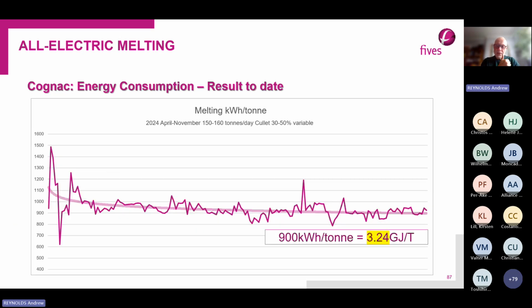That's the actual data, a snapshot of the data on the energy consumption. So you can see that the up and down is simply that they do job changes. So the load on the furnace is continuously changing. The cullet content is changing. So you don't get a perfect straight line, but it's tending towards the 900 kilowatt hours per ton, which was predicted. So it's behaving exactly as we anticipated.